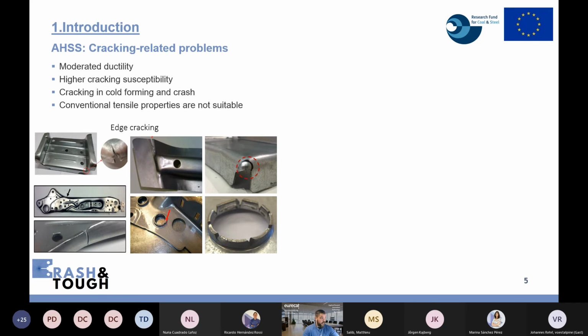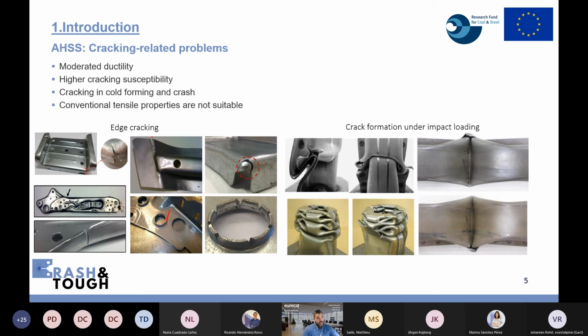Some real-life examples are the occurrence of edge cracking during cold forming, which is more and more recurrent with the use of advanced high-strength steels. So as we move to steels with higher and higher strength, it's probably more frequent. Also, another kind of problem related to crack formation is the crack formation under impact loading. For example, we can see here samples that have been crash tested, and we can see some of them show this degree of necking. As I mentioned, these fractures are more and more frequent with this kind of advanced high-strength steels.